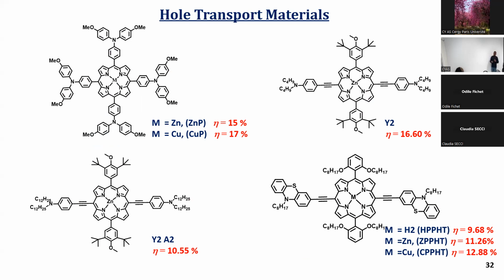Previously, a molecule with around 16% was reported, based on porphyrins with different centers, A2B2 porphyrins, with different alkyl chain lengths giving the highest efficiency. These molecules gave 15%. After that, in my research group and my PhD work, I was involved in perovskite solar cells, mainly synthesizing hole transport materials. We synthesized donor-π-donor concept based phenothiazine molecules. With different metal centers, we reached the highest efficiency in our laboratory, 12.88%.